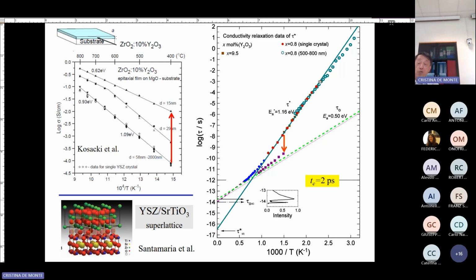You look at this one with the bulk. They are going to 10 to the minus 17 seconds, which is very unphysical. You don't have vibration or attempt frequencies of the ion like this. We already know it from Raman scattering. The oxygen atom is known by Raman. It's over here, 10 to the minus 13.5, the main peak here. That's the oxygen vibrational attempt frequency.